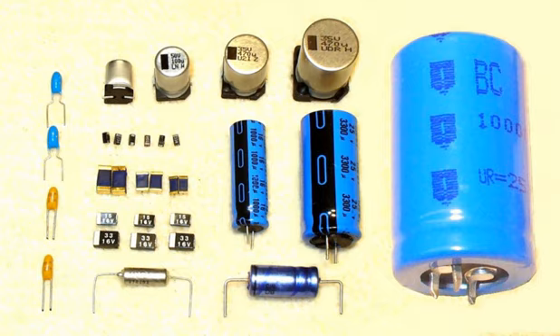They ground tantalum to a powder, which they pressed into a cylindrical form and then sintered at higher temperature between 1500 and 2000 degrees Celsius under vacuum conditions to produce a pellet slug. These first sintered tantalum capacitors used a non-solid electrolyte, which does not fit the concept of solid electronics. In 1952, a targeted search at Bell Labs by D. A. McLean and F. S. Power for a solid electrolyte led to the invention of manganese dioxide as a solid electrolyte for a sintered tantalum capacitor.